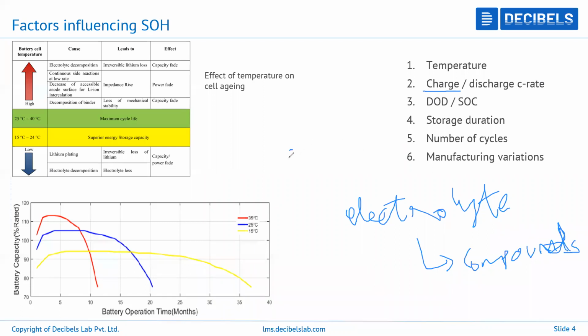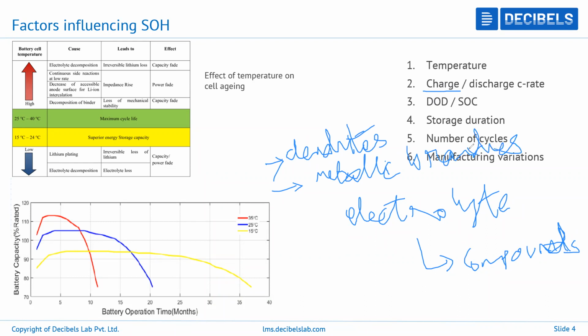So again, here we'll have things like dendrites. And we'll have something called metallic branches. These are basically metal compounds that form due to unreacted lithium, and they will form metallic branches, and this will again cause thermal runaway. So that is the effect of having high charge C rates. Similarly, you will also see that high discharge C rates will once again wear away at the electrodes, even the electrolyte. So it's always better to sustain the cell within the recommended charge and discharge C rates.